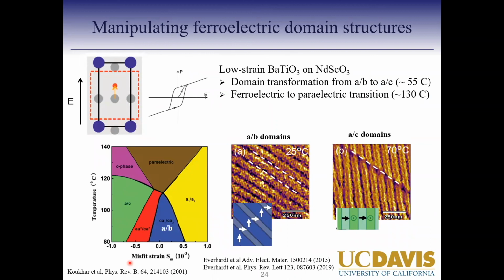So for these particular domains, they haven't done that yet. These phases were stabilized in 2015, 2019 in these systems. There's a study from 2019, published in a PRL, where they did imaging using PFM, piezoelectric force microscopy. There they don't see the timescales, but they just see the distribution of the material. So there's not a real space study out there. That's related to the fact that, how would you image ferroelectric domains? Either you use PFM, you use TEM, or you use some sort of X-ray diffraction imaging technique.